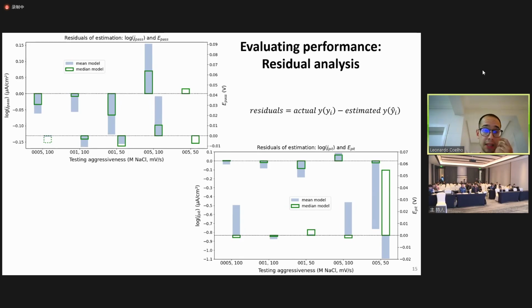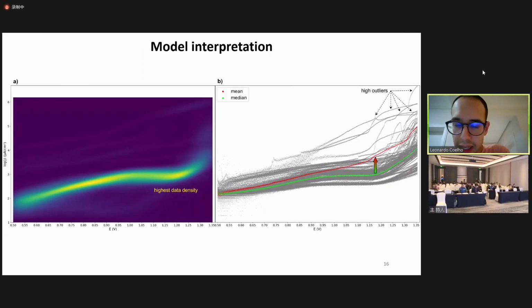And well, the advantage of these proxy models is that they are much easier to interpret than a machine learning model. So we understood that the median model was performing very well because it really corresponded, I showed the median in green on the right, to the highest data density regions from the data population. And strikingly, we were able to immediately see why the mean curve was shifted upwards. This was due to the effect of high outliers.